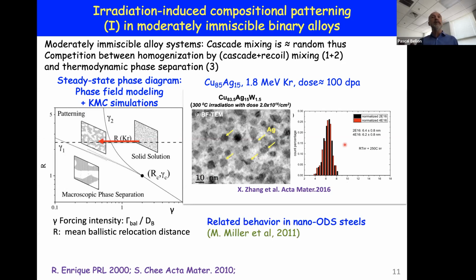So in some ways, it's quite similar to the behavior observed in nano oxide dispersion strengthened steels, where the inclusions were nano oxide precipitates, but here it's done with metallic precipitates. And in this particular case, we know that under the conditions I'm showing you here, these precipitates will never dissolve under radiation, because this is the regime where they are stable. And we know this guided by the steady state phase diagram on the left here.